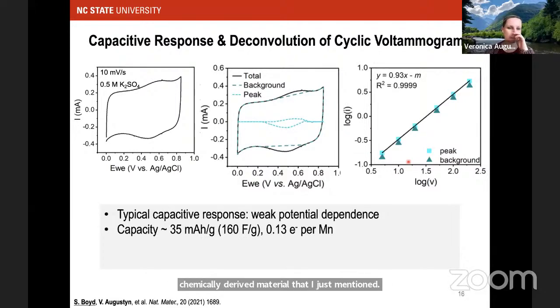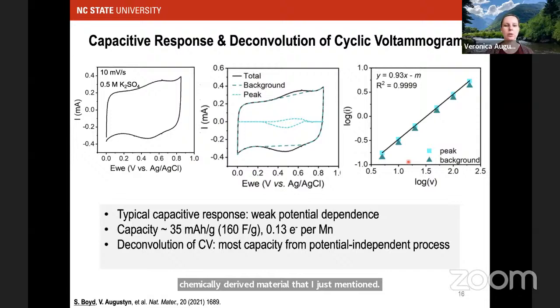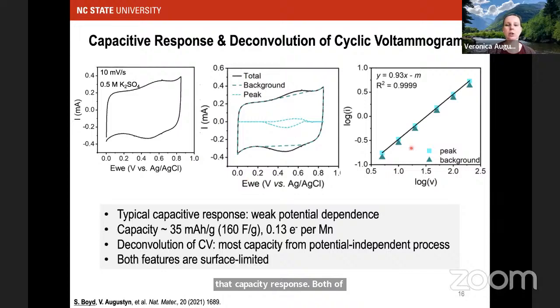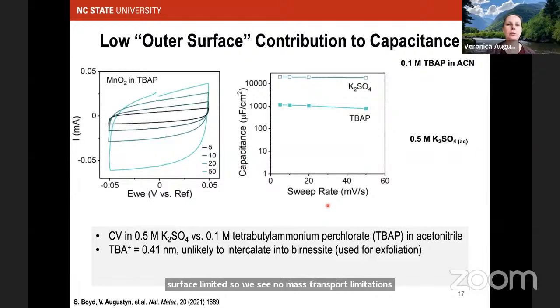The capacity is modest. It's about 35 milliamp hours per gram, or about 0.1 electrons per manganese that are being stored. Most of the capacity is coming from the potential independent process. So we can do a little bit of a cyclic voltammetry deconvolution into a perfectly rectangular response. And then this peak-shaped response, most of the capacity is obviously coming from that capacitive response. Both of these features are surface limited, so we see no mass transport limitations in the material.